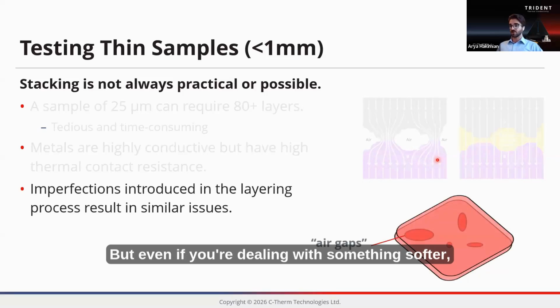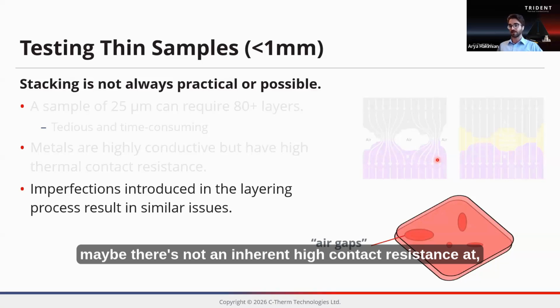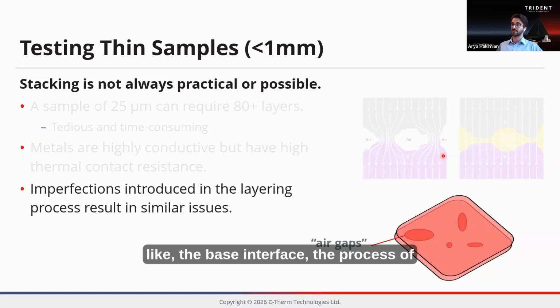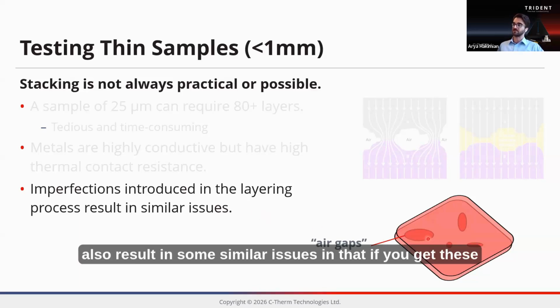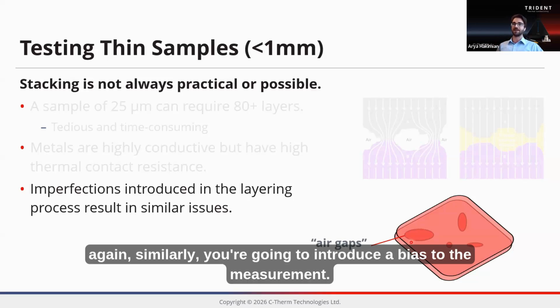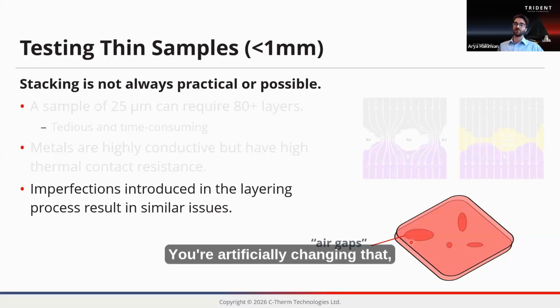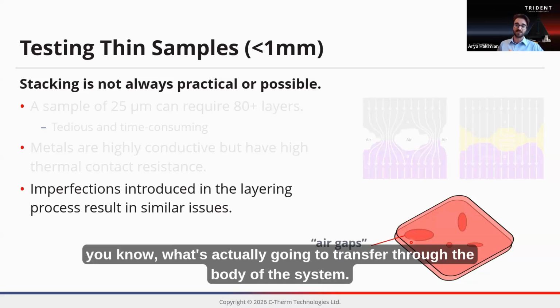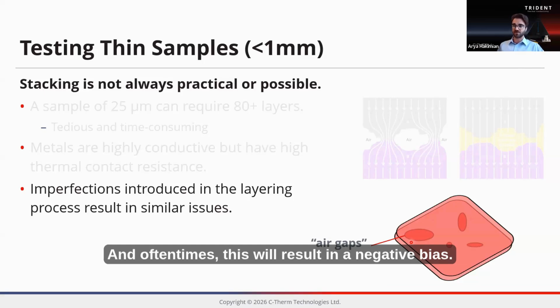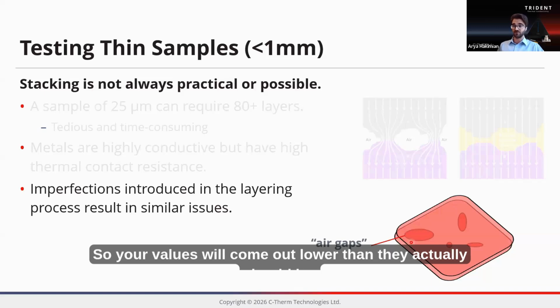But even if you're dealing with something softer, maybe there's not an inherent high contact resistance at the base interface, the process of actually layering the sample can also result in similar issues, in that if you get these imperfections or gaps forming between those layers, similarly, you're going to introduce a bias to the measurement. You're artificially changing what's actually going to transfer through the body of the system. And oftentimes this will result in a negative bias, so your values will come out lower than they actually should be.